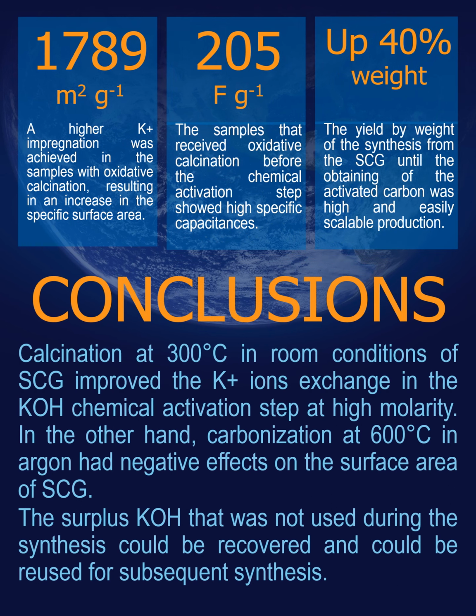Concluding with this work, we have that an oxidative calcination at 300 Celsius degrees at room conditions of the spent coffee grounds improved the potassium ion exchange in the potassium hydroxide activation step at high molarity, specifically at 6 molar. Thanks to that ion exchange, the surface area increased after the heat treatment, and due to the synthesis path, the number of functional groups was also increased, thus improving the electrochemical performance, both by the formation of electrochemical double layer and the pseudocapacitance.